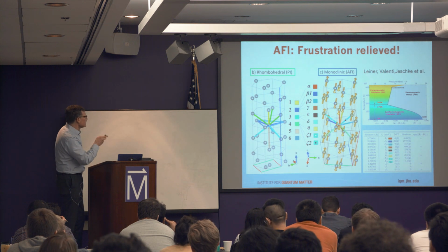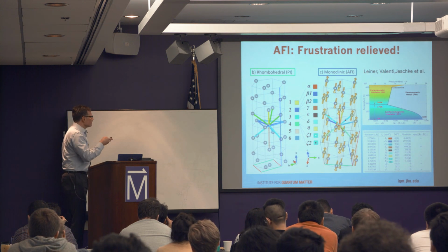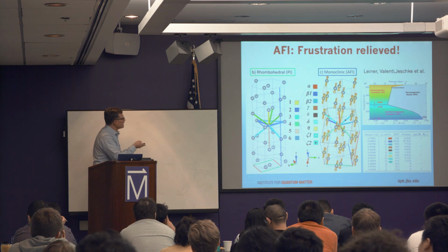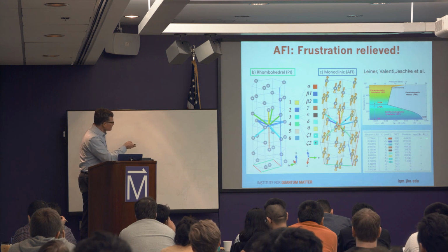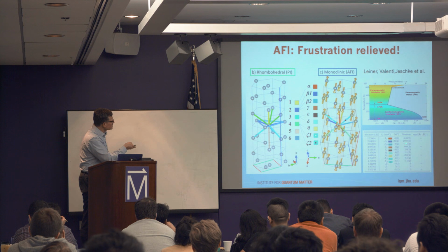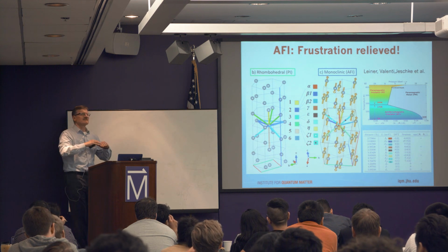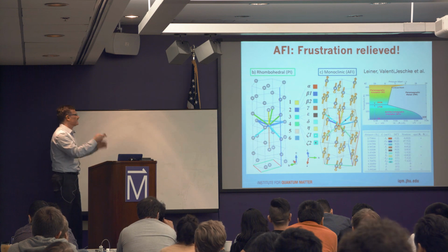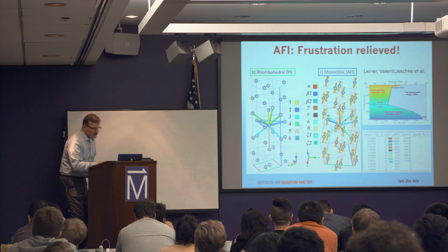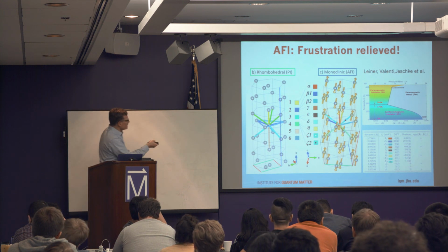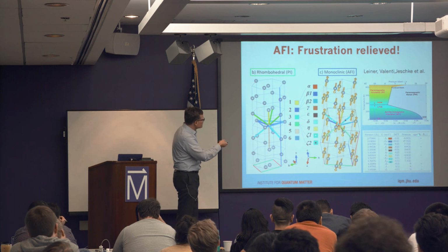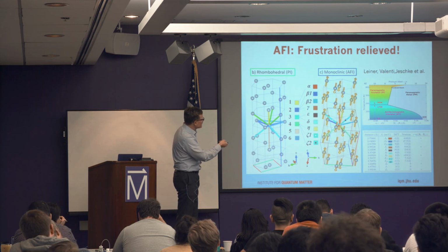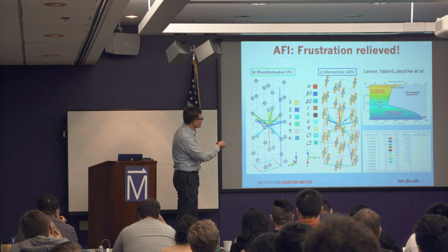neutron experiment. And the very significant feature that I wanted to point out is that every single one of these interactions actually turns out to be satisfied. I have to explain what I mean by that, but satisfied in the ordered magnetic state. And what we can say is that here is shown the sign of the dot product between the neighboring spins connected by this exchange constant.